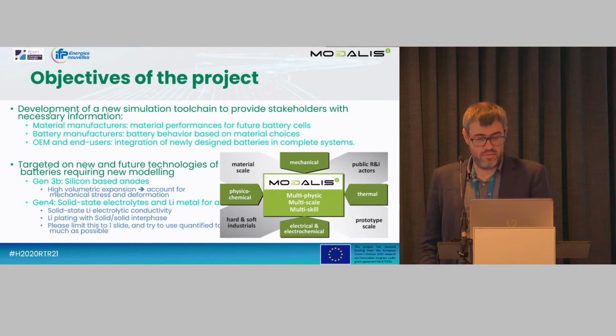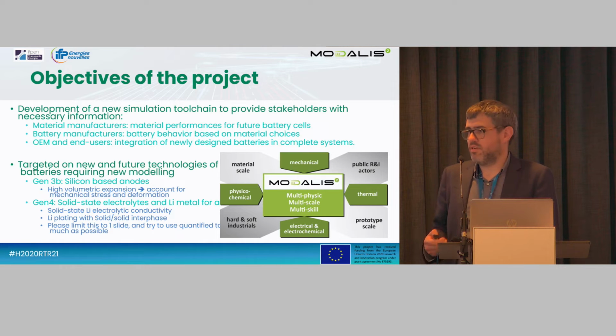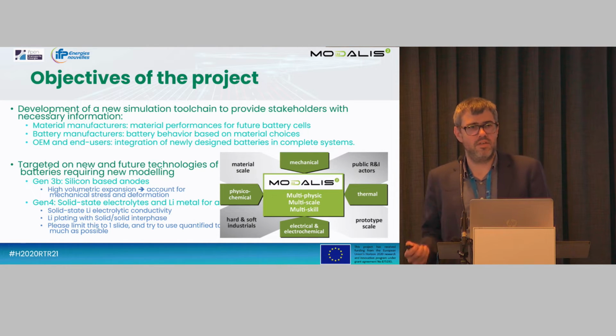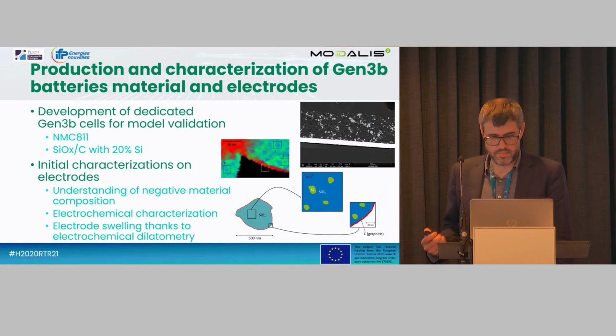And for generation 4 batteries, we need to focus on solid-state electrolytes, and especially the ionic conductivity in these solid-state electrolytes, how it behaves and what are the main differences compared to liquid batteries. And the main issue is that we have a lot of interfaces, and we wanted to focus on this interface to see their impact, how we can model it, and how we can take into account the change in the behavior of the interface along the lifetime of the battery.